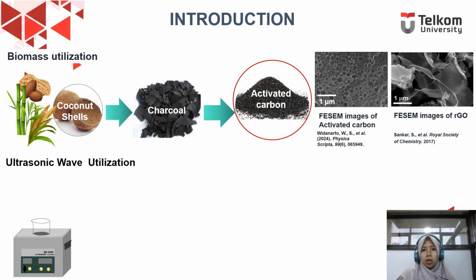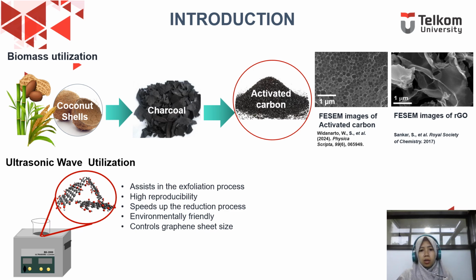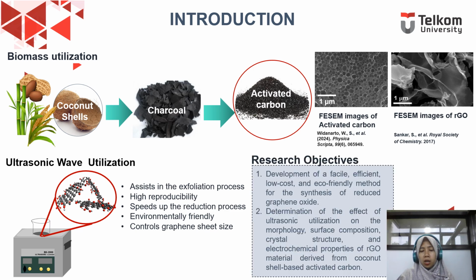the graphene-like material. The utilization of ultrasonic waves offers several advantages, such as assisting in the exfoliation process, high reproducibility, speeding up of reduction process, environmentally friendly, and control of graphene sheet size. Hence, this study aims to, number one, development of a facile, efficient, low-cost, and eco-friendly method for the synthesis of reduced graphene oxide. Number two, determination of the effect of ultrasonic utilization on the morphology, surface composition, crystal structure, and electrochemical properties of RGO material derived from coconut shell-based activated carbon.